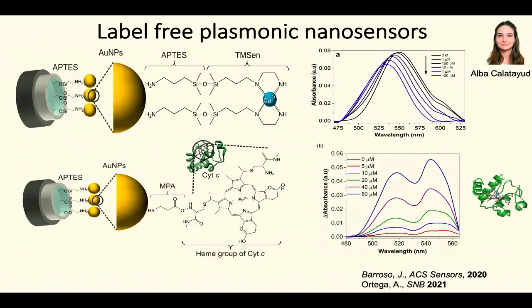Finally, we did another experiment. It's a replica of the experiments made with the dark field microscope by Lourdes, where we functionalized with a molecule that was able to interact with cytochrome C. And upon the interaction of the cytochrome C with the gold nanoparticle, we could very nicely see the spectra of the cytochrome C through the spectra of the gold nanoparticle. We could also detect this cytochrome C in plasma samples.